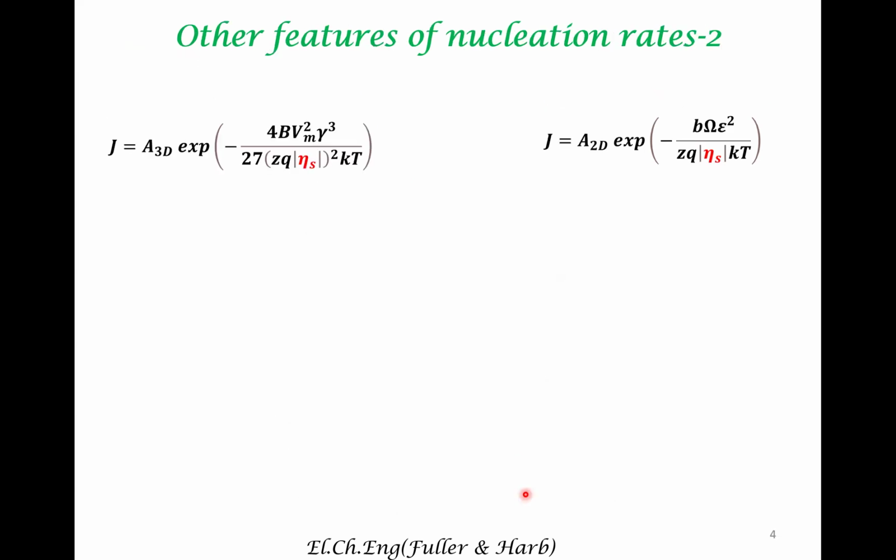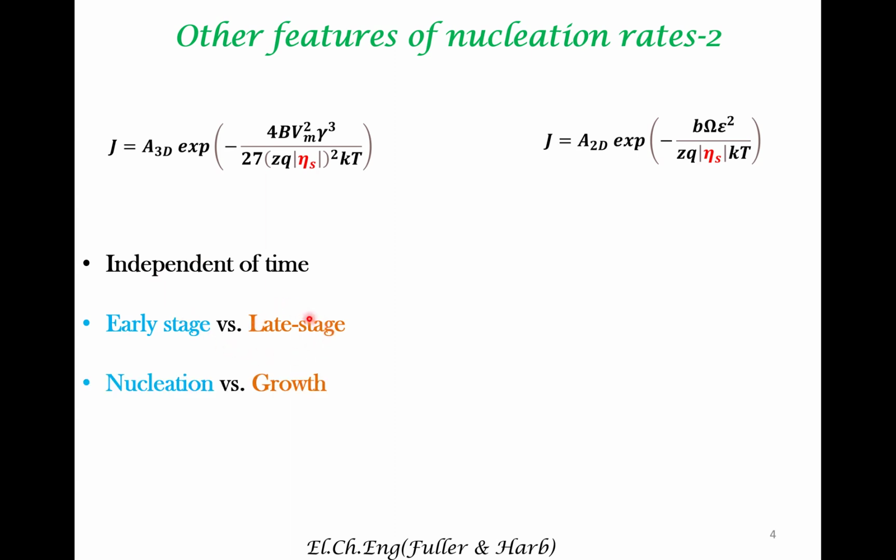Moving on, what we see from the expressions projected in the previous slide is that the nucleation rate is independent of time. Within the models which we have derived, nucleation is independent of time. This sort of makes sense, especially when you divide the nucleation and crystal growth into early stages and late stages of crystal growth. In the early stages, we are usually focused on nucleation. This is the main physicochemical event that occurs.